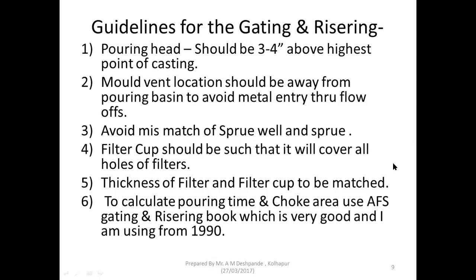Normally, what happens, if the thickness of the filter is less, the sand will fall. And if it is more, the slag will flow away. So the thickness of filter and filter cup has to be matched perfectly. It should be within 0.5 mm, we can say.